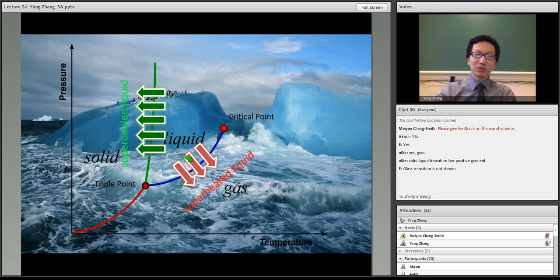Superheated liquid is relatively easier to understand because the temperature is high and the system is ergodic. Although it's a metastable state, the dynamics are relatively fast, so it's easier to understand. But for the supercooled liquid, the dynamics is very, very slow. And if you keep going down, eventually it will form a glass.